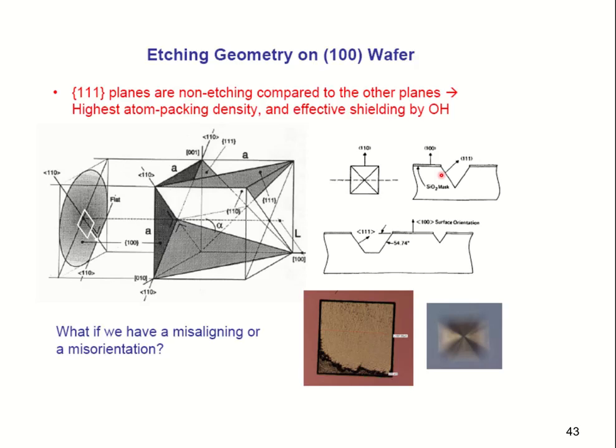The ratio is 400 times or 200 times faster than the etch rate of 111. That's why you have a particular angle, which is 54.74 degrees. That's the crystal direction. So you have a particular shape with this angle of 54.74 degrees. This is one example. If you have a misalignment, the problem is that your crystal structure and your mask pattern are not well aligned. Then when it starts cutting down, it keeps being misaligned. So at the end, it's not a clear pyramid shape anymore. It's a misaligned pattern.